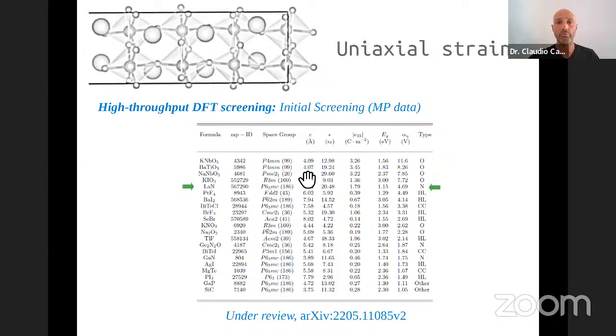So here is the space group, right? And all the properties. All these are non-polar materials. We have the electric properties. We have the piezoelectric coefficient, the band gap, etc. And finally, the value of this alpha eta, right? Of course, for having a large alpha eta value, you need to have a combination of two properties that is not common, right? So you need to have a high e33 piezoelectric coefficient, and at the same time, you will ideally need to have a small dielectric constant, right? Because this dielectric constant goes into the denominator of this descriptor here, right?